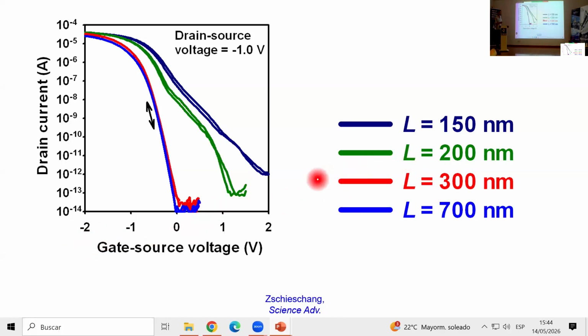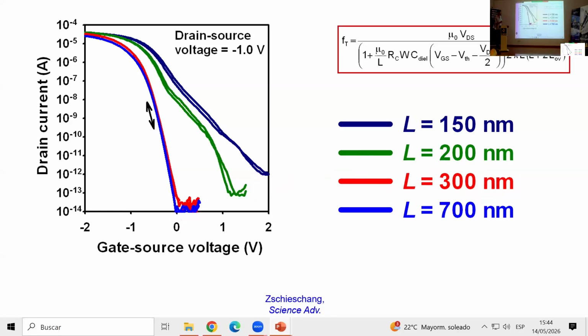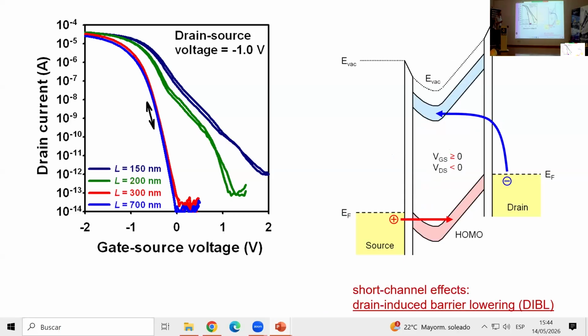But we also see that when the channel length drops below 300 nanometers, the off-state drain current increases by an order of magnitude by going from 300 to 200 nanometers, and by another order of magnitude by going from 200 to 150 nanometers. So clearly, when a channel length is below 300 nanometers, something bad happens. And that's not too surprising, because when we make the channel length too small, we induce basically tunneling through this barrier of holes from the source contact into the HOMO gap, okay?